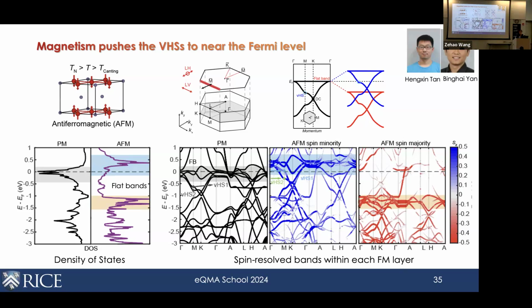Is there any interplay between the CDW and the magnetism? That's a good question. The magnetic moment below the CDW order is enhanced, as seen by neutron. The Néel temperature is 410 Kelvin, and the CDW is around 100 K. From neutron, you can see an enhancement of the moment below the CDW order. The CDW is 2 by 2 in plane, and there's an out-of-plane component as well.